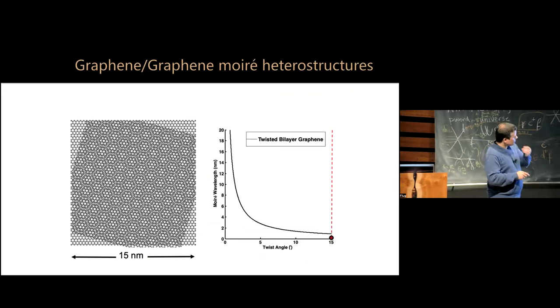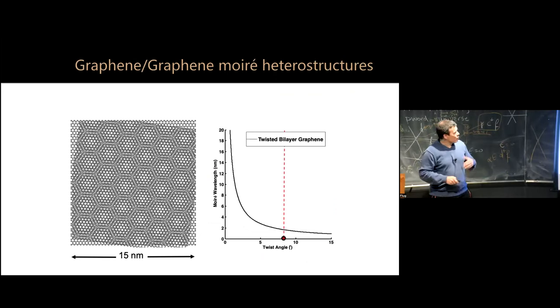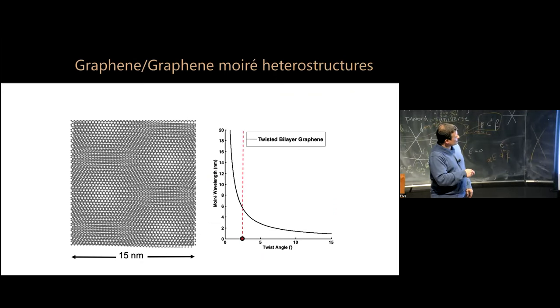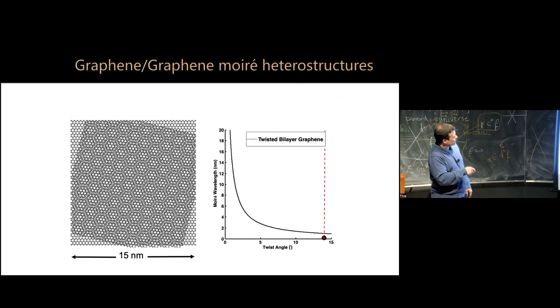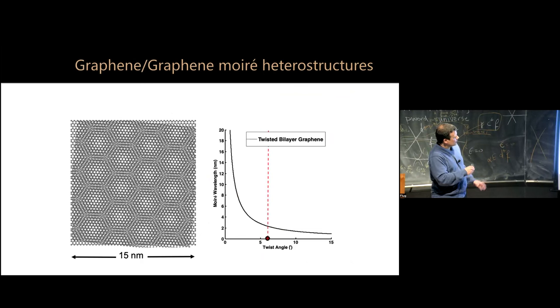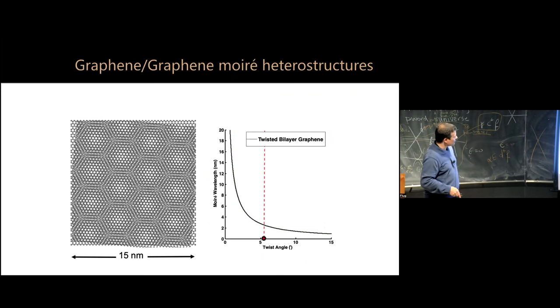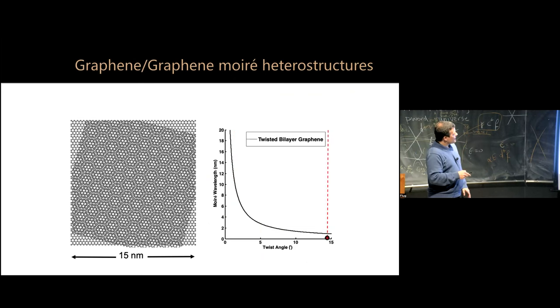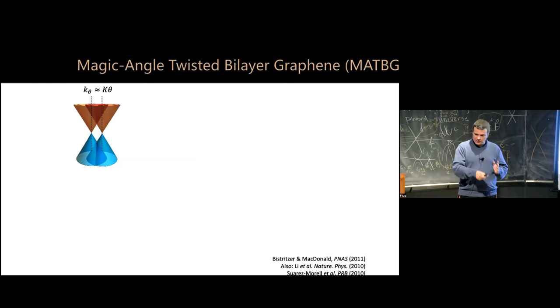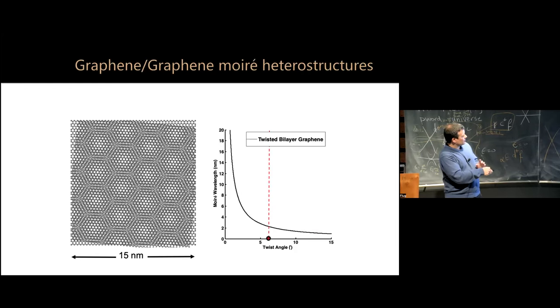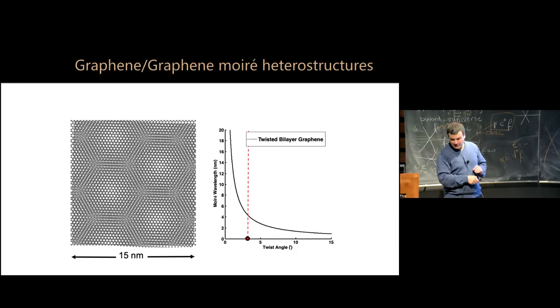Now, if you put graphene on top of graphene, you create a moiré pattern. And the moiré wavelength, which means the distance between the soccer balls that you see here on the screen, depends on the twist angle, okay? Now, let me take 2 graphene sheets. So this is what happens when you put graphene sheets on top of each other in real space.